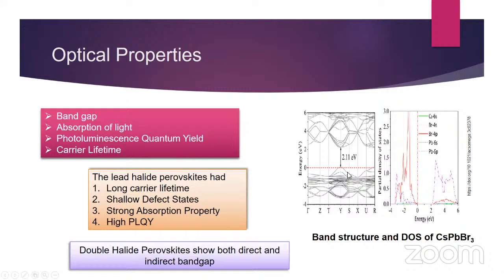Okay, so the optical properties of the materials are very important because of these optoelectronic applications. The band gap is one of the most important properties of the materials as it decides the applications. Also, the absorption coefficient, PLQY, and carrier lifetime are important for device fabrication. Lead halide perovskites had longer carrier lifetime, shallow defect states, strong absorption, and high PLQY. Because of these properties, lead halide perovskites were very much liked by scientists for optoelectronic applications.